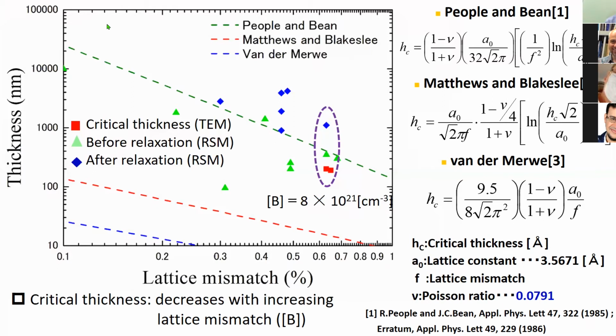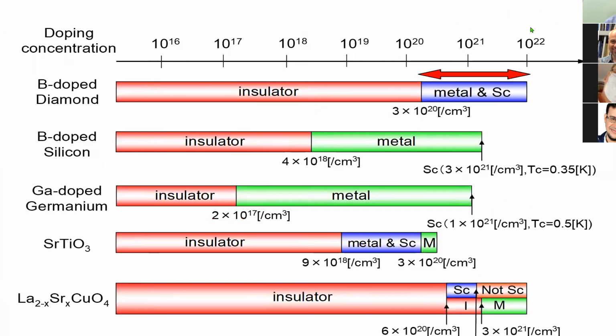So I just summarize other materials and their doping concentrations at TC, and what we have in diamond. You can see diamond placed like that, 10 to the 20s, and in these regions also boron doped silicon or gallium doped germanium. Or recently, boron doped silicon carbide shows superconductivity. This is a French group, the same group that did diamond, and they showed nice results in silicon or germanium, I think.